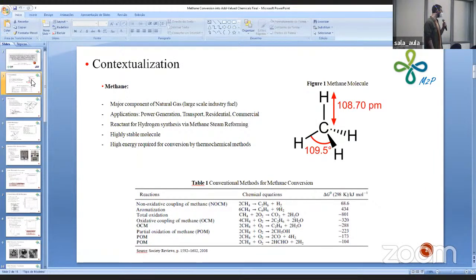have shown that those thermochemical methods for methane conversion are only viable for hydrogen synthesis via methane steam reforming. Otherwise, the severe conditions tend to disfavor the reactions from occurring. Some of those reactions are presented here in table 1, and we have some reactions of non-oxidative coupling of methane and aromatization of methane to higher hydrocarbon chains.